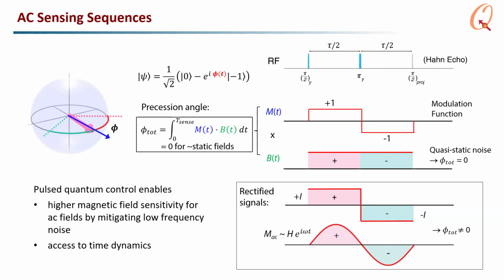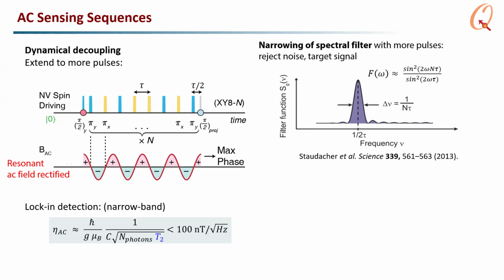And this is beneficial because it reduces noise and extends the coherence time of the NV center. That was an example with just one pi pulse, but what you want to do is put in even more pi pulses. If you put in more pi pulses, the frequency that you're sensitive to gets more and more narrow, at the frequency where you switch sign at every pi pulse, and then you're rejecting more and more noise and isolating your target signal. This is exactly the same as classical lock-in techniques, except for the quantum system, it has to be completed within the coherence time of the NV center.